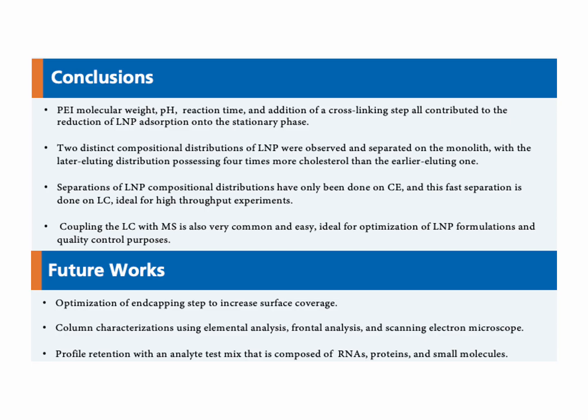To conclude, PEI molecular weight, pH, reaction time, and addition of cross-linking step all contributed to the reduction of LNP adsorption onto the stationary phase. 2 distinct compositional distributions of LNP were observed and separated on the monolith, with the later eluting distribution possessing 4 times more cholesterol than the earlier eluting one.